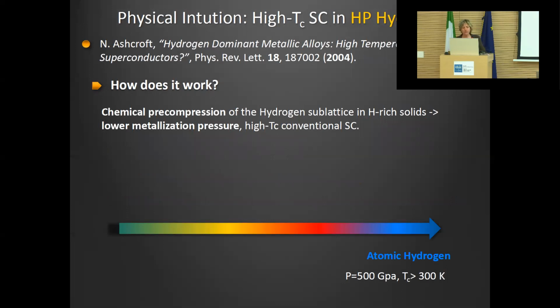So we have seen hydrogen. What is the problem with hydrogen? I draw an arrow here, and this arrow should give an idea more or less of the evolution of the properties with pressure. So at the far right end of the spectrum, we have atomic hydrogen. And as you see here, the pressure that you need to metallize hydrogen, now we know it, is around 500 GPa. You would expect critical temperatures which are larger than 300 K, so larger than room temperature, but in order to measure this critical temperature, one would have to achieve pressures of the order of 500 GPa.